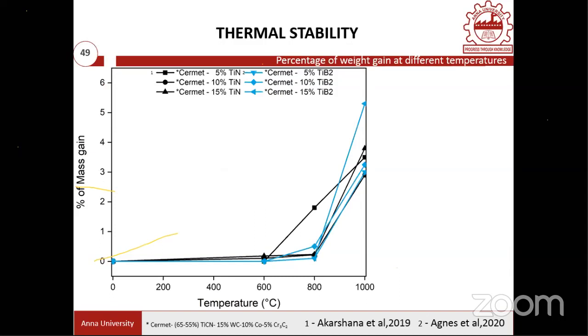So mass gain is proportional to the oxide formation. When the tool material is engaged in ambient atmospheric conditions where oxygen is there at high temperature, the oxygen can react with your tool material or work material, and it can be easily oxidized. Therefore, the oxidation-based wear mechanism is also one of the responsible mechanisms for wear in the cutting tool. Therefore, here we are measuring the mass gain.